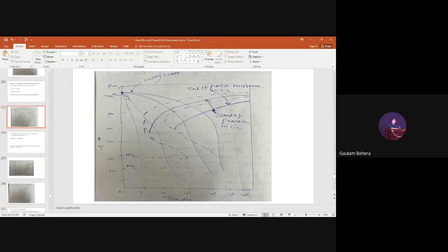But martensite basically forms if you do continuous cooling. We also know you can do isothermal cooling, no problem, so martensite will still be there. In the CCT diagram, you can also show martensite start temperature and finish temperature. That means something is absent. What is absent here? Bainite. Bainite is absent. Very good.